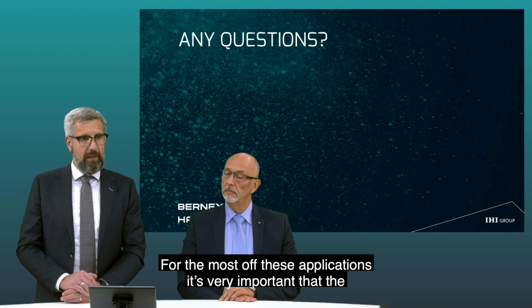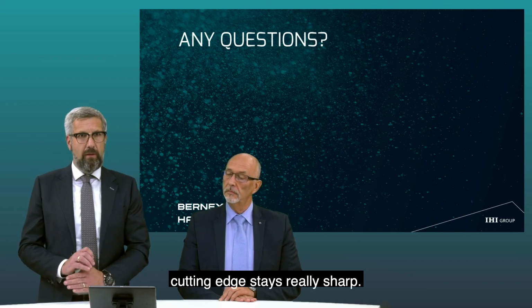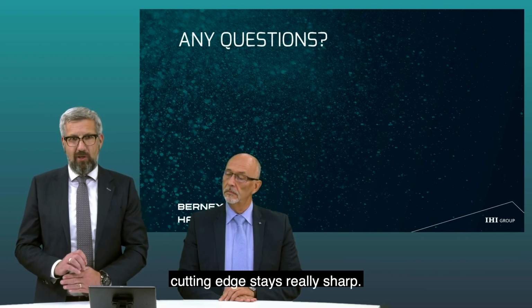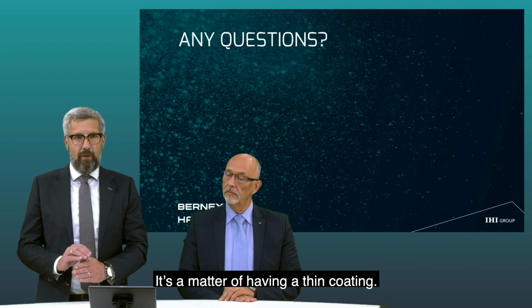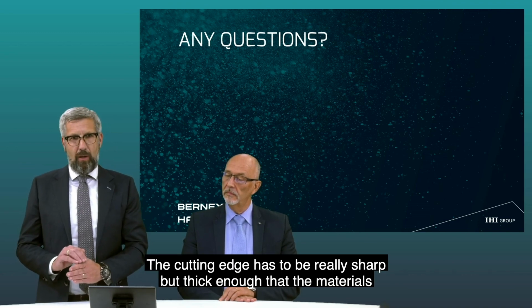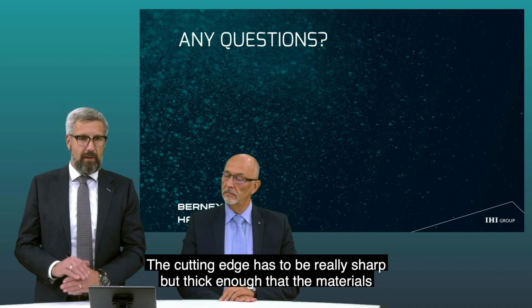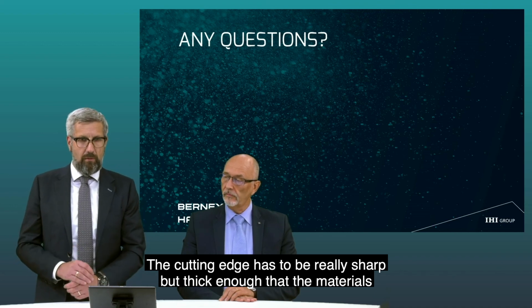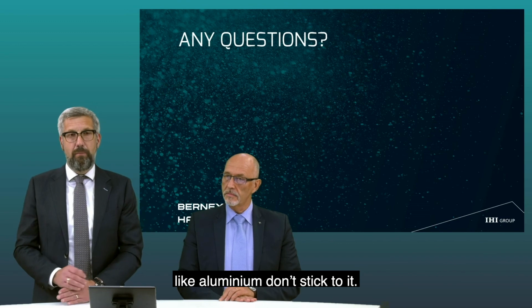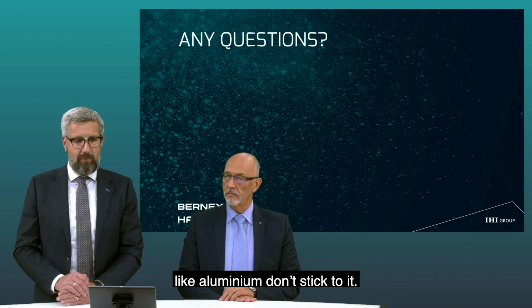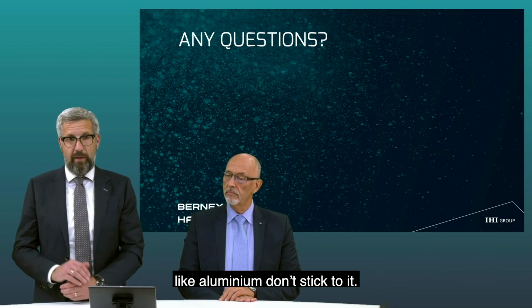For most of these applications, it is very important that the cutting edge stays really sharp. So it's a matter of having a thin coating to still have the cutting edge really sharp, but thick enough that the small particles from the aluminum don't stick at the surface of the drill or the mill or whatever it is.